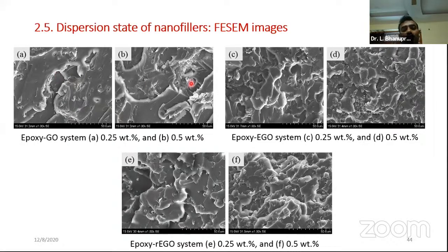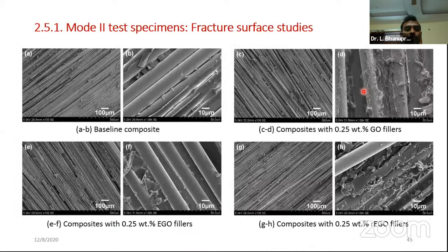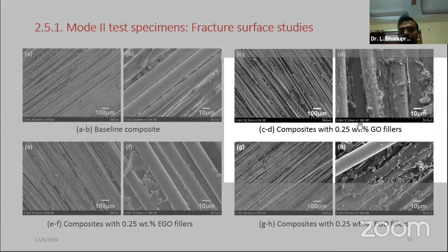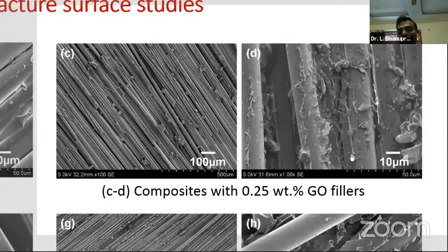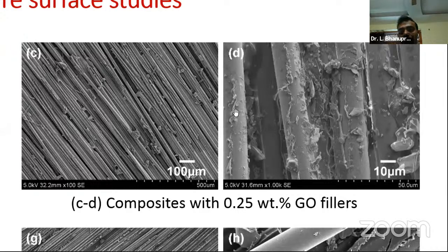The nanofiller dispersion has been studied. Also, the fiber surfaces here, you can see. These are the clean fiber surfaces in the baseline composite without nanofillers. Fiber surfaces are very clean. And you see with the GO as well as REGO, see how the fibers are being tightly wrapped up with the matrix material because of the presence of nanofillers. See the layer of matrix that has been tightly adhered onto the fibers. So that is how the physical bonding is being improved with the presence of nanofillers.